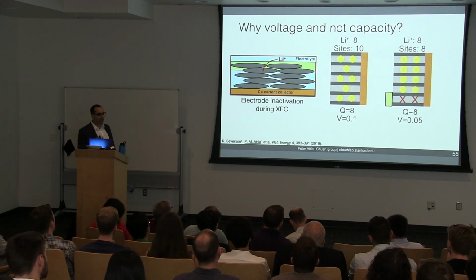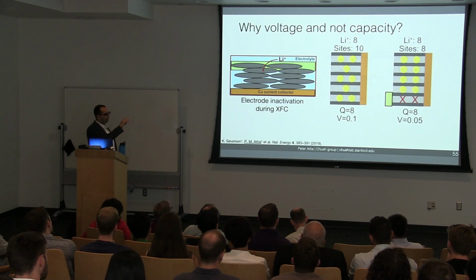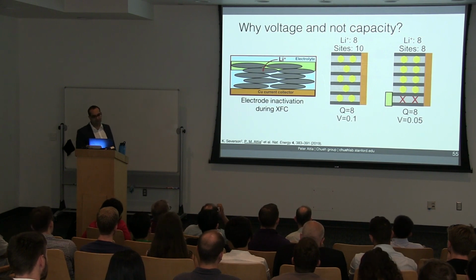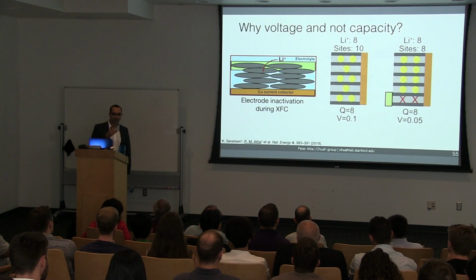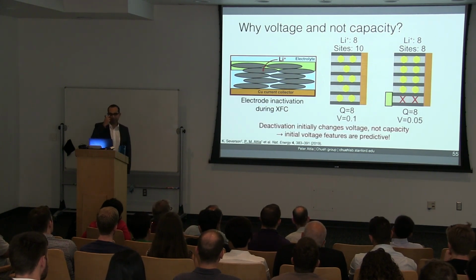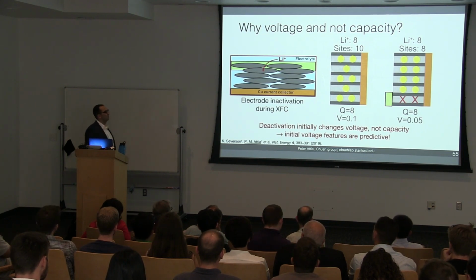Batteries are typically designed with more graphite sites than lithium ions. Let's imagine we lose an active site, but we still have more graphite sites than lithium ions. The capacity doesn't change, but the voltage changes because the crystallographic ordering of lithium and graphite is now different. So the voltage features from the first 100 cycles are predictive because electrode deactivation initially only changes the voltage, but not the capacity.